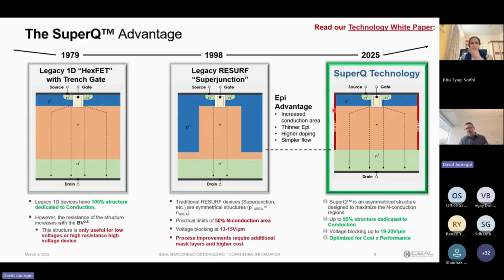We're relying on what we call a charge layer or charge dielectric, and it's very, very thin. As a matter of fact, it allows us to revert back to the HEXFET days, where we had these very wide conduction regions and these very narrow charge compensation regions. So these red lines that are parallel to the mesa create the same charge compensation function that you saw with this P plus. We're only doing it in a much smaller area.